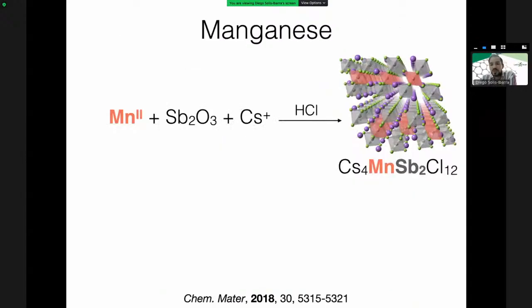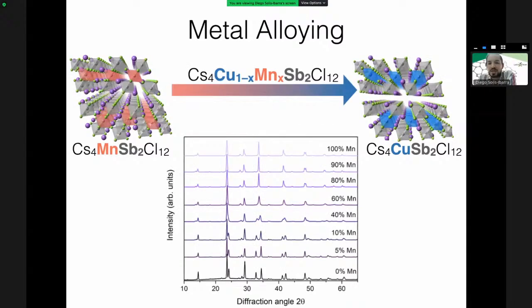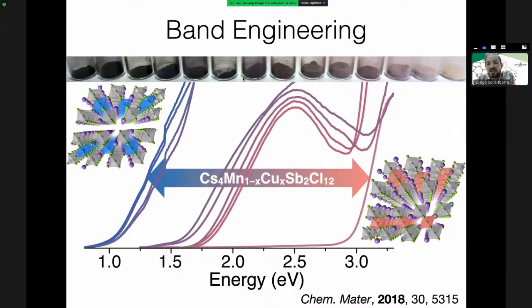So Brenda was quick to prove that you could also put manganese instead of copper, and when incorporating manganese, you also change the properties of these materials. Also, very importantly, you can modulate the amount of manganese. You can do solid solutions and progressively introduce different amounts of manganese on these materials. And what this results in is a modulation of the bandgap of these materials and the properties of these materials.